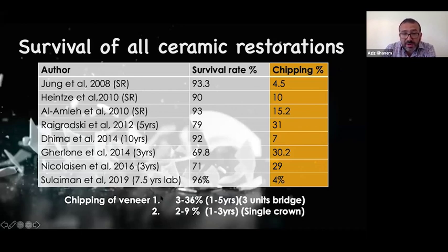the layering of zirconia and the incidence rate of fracture or chipping of that has been reported at about 3 to 36% from 1 to 5 years for 3-unit bridges. Okay, and these numbers are mainly for zirconia core. And the chipping for the single crown from 1 to 3 years is 2 to 9% chipping rate.